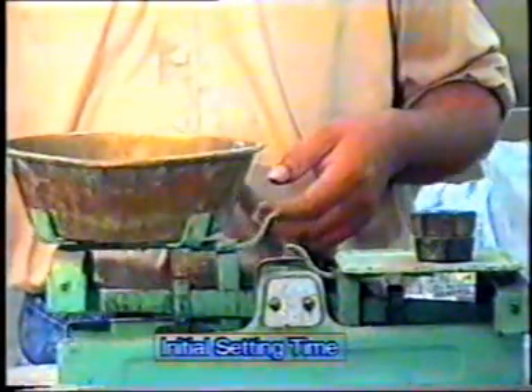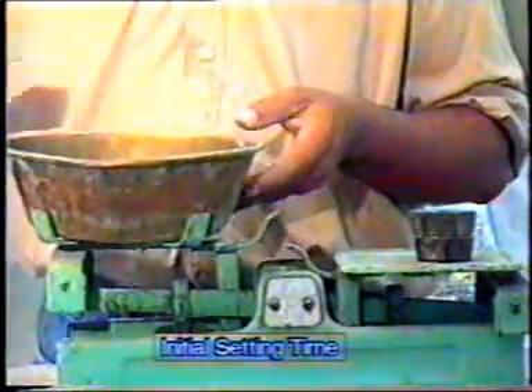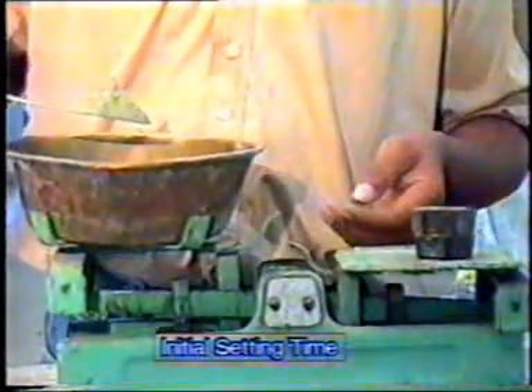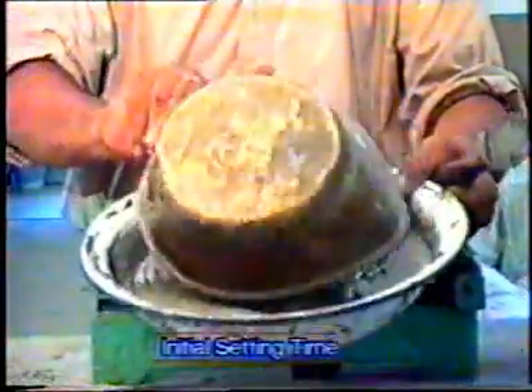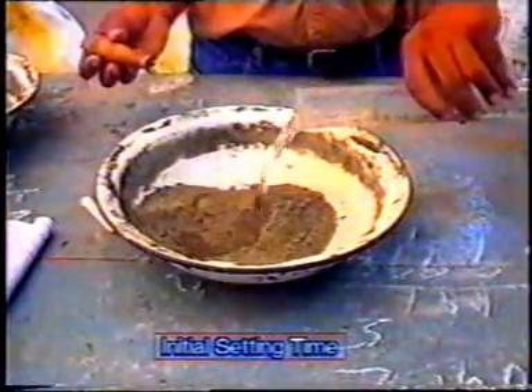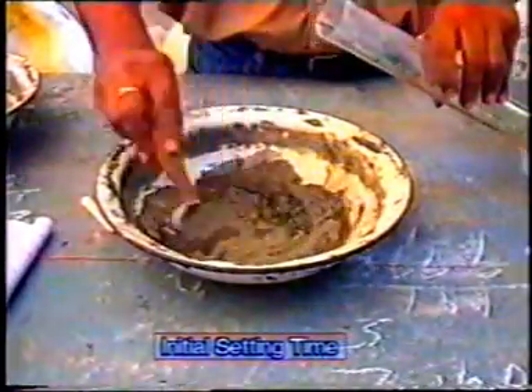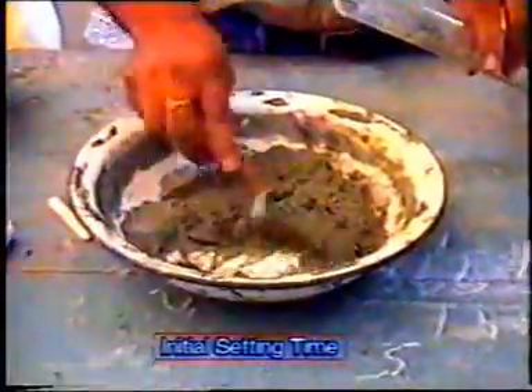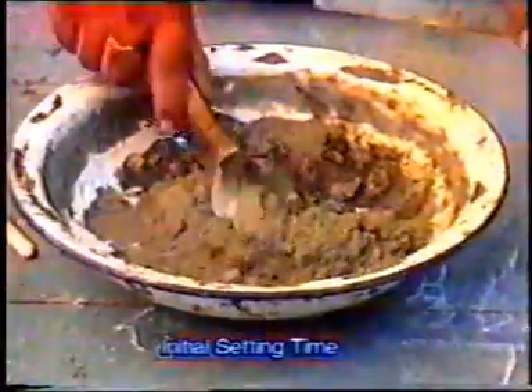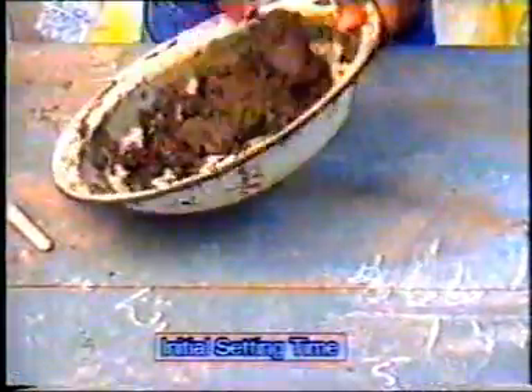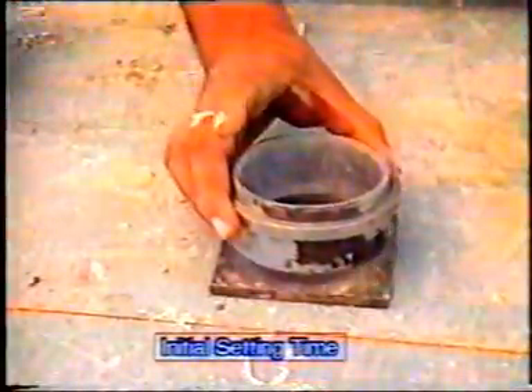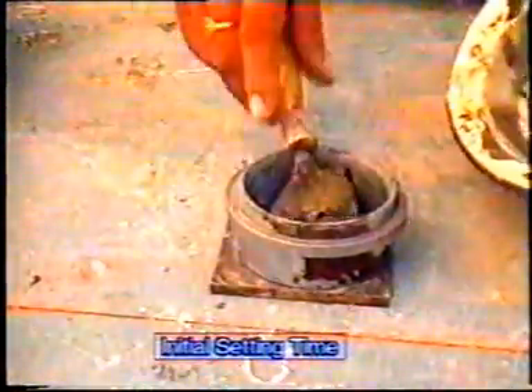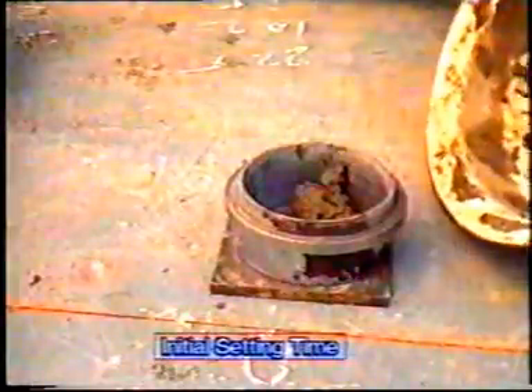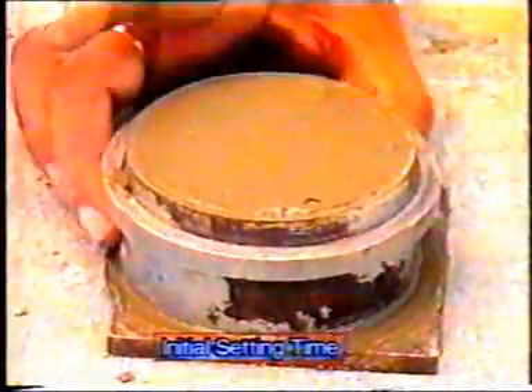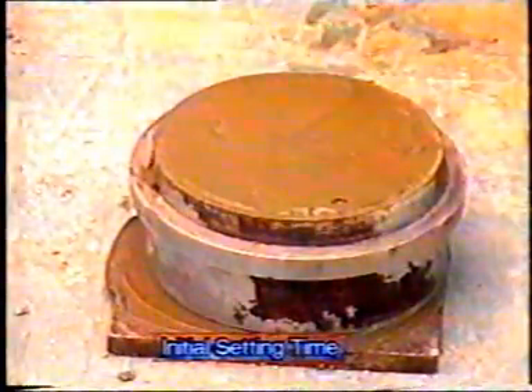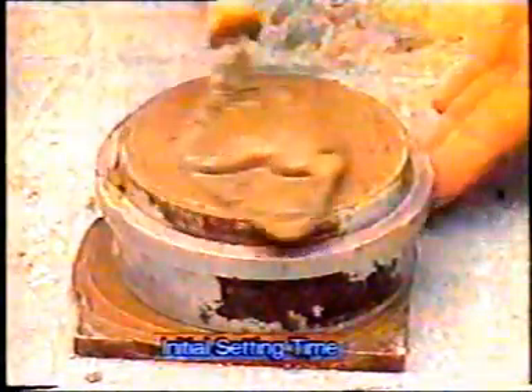Preparation of test block. Take 400 grams of cement into a porcelain dish. Add 0.85 times the quantity of water required for normal consistency. Mix the paste thoroughly and place the paste in the Vicat's mold, which is placed on a non-porous plate. Start the stopwatch at the instant when the water is added to the cement.